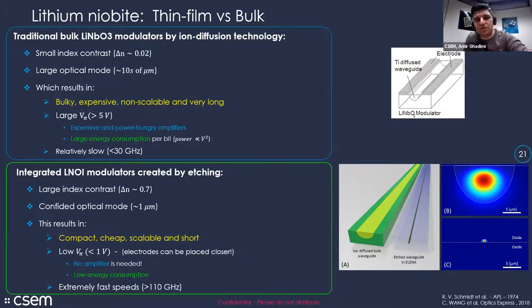So how they traditionally used to make modulators and waveguides: the traditional method was to take a crystal of lithium niobate and make waveguides by doping some regions in it, in the same way you make optical fiber. By using these titanium diffusion waveguides, you can create a region slightly higher doped to create a small refractive index contrast to confine the light. But the downside of this bulk technology is that the refractive index contrast you generate with this method is very small. So delta n is in the order of 0.02.